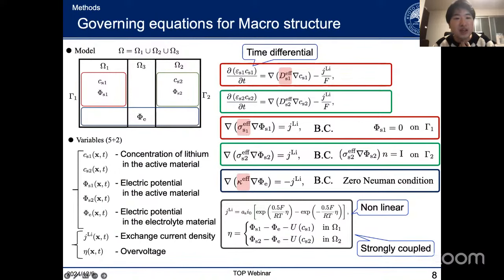Here is the governing equation for ASSBs and the macro governing equation. Five variables should be defined to solve ASSBs. The first two are the concentration of lithium in the active material for each region. Phi S1 and phi S2 are the electric potentials in the active material, so we need to define two regions. The last one is the electrical potential in the electrolyte material. The electrolyte is distributed in the whole region, so only phi E is defined in the whole region. J lithium and eta are the exchange current density and overvoltage respectively.